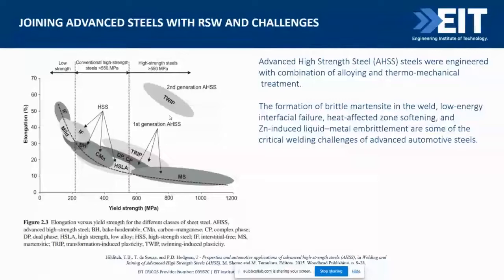Now, high strength steels, no doubt they are quite strong, but they will never give you a pull-out failure. As I mentioned a while ago, the spot weld requirement in the automotive industry is that you need to get a pull-out failure. That means the weld nugget should be pulled out from one part of the steel, while on the other steel it stays stuck. That's the pull-out failure, which typically shows that the spot weld is able to absorb a lot of energy. In advanced high-strength steels, no matter how strong the weld is, it will crack via interfacial failure, because due to welding, because of the use of heat and so on, the whole weld will be martensite. Martensite is a microstructure that is always hard and brittle. So these welds will naturally break.